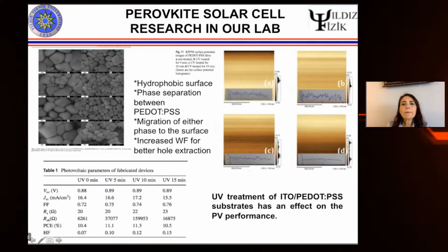And here, since this is the PIN structure, we don't have the ambition for our perovskite to diffuse to the pores of the system, because this is not a porous system. And here, the hydrophobicity of the surface is important for us. And we have realized that when the surface is hydrophobic, we have larger grains without any kinds of defects here at the surfaces.